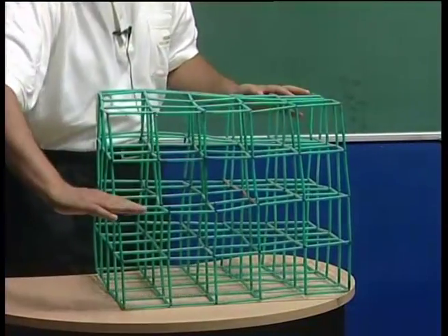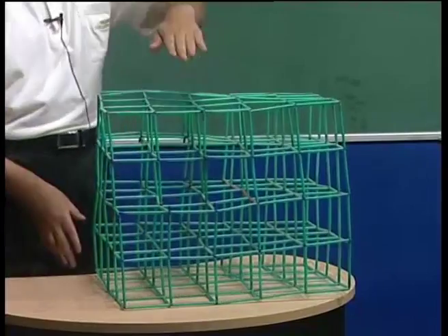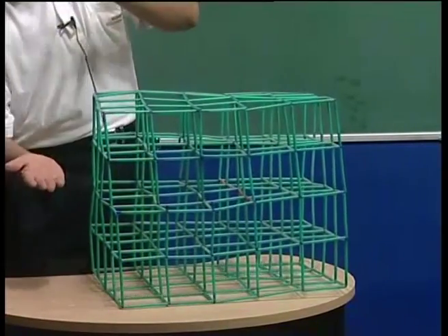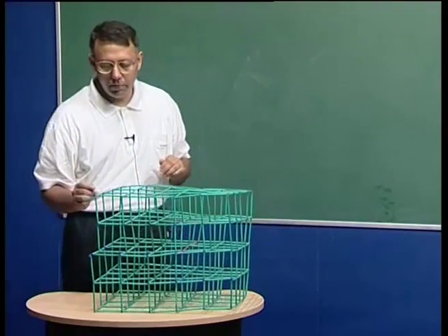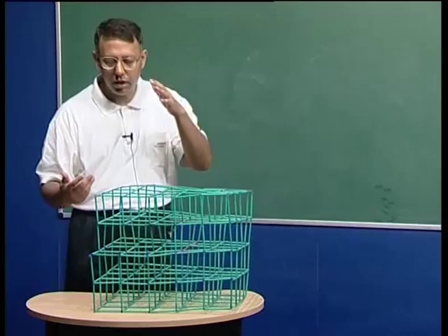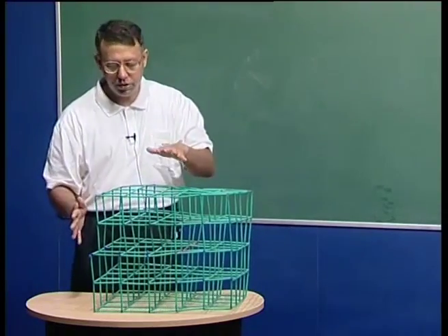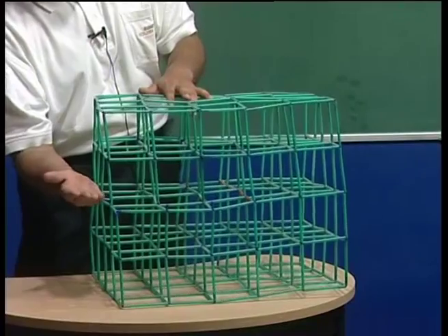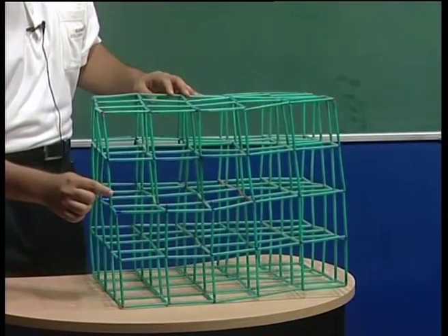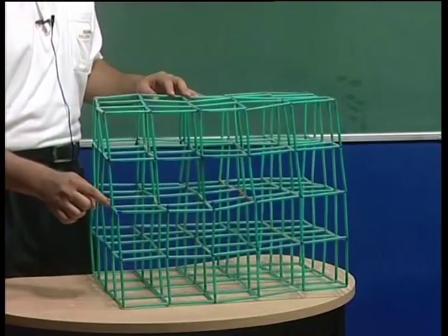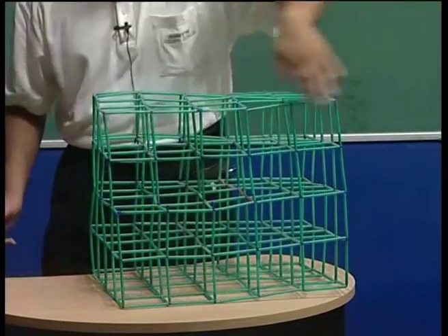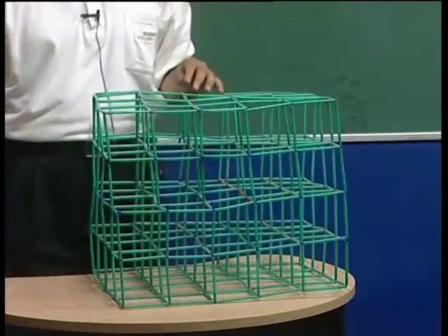So, the shearing direction, of course, is this, that means I have taken this and pushed my crystal in this direction towards me, that means my shearing operation is going like this, that is before joining. I make a cut, this cut is of course hypothetical, I am doing a mental construct to get this dislocation. I make a cut in this crystal here, I shear the crystal and join, whatever originally this bond must have gone here, I put it here, and therefore I get planes which are now bent around this place.